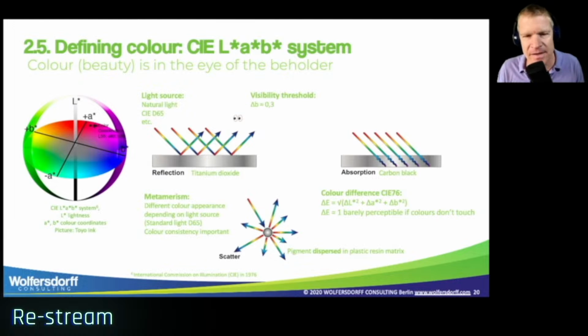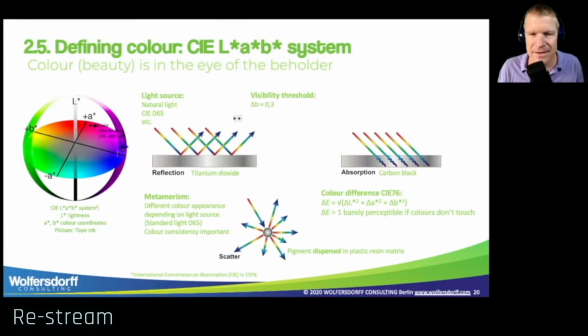And then looking at the masterbatch, we have several mechanisms by which the light can engage with our pigments. That could be reflection, which is the case of titanium dioxide, with the highest refractive index of all materials. This is the reason titanium dioxide is used as a white pigment, because all the light is reflected. It could be absorption, which is the case of carbon black. So we expect from carbon black, and also from recovered carbon black, to absorb all the light and to appear black, because black is the absence of any light. And then we might have scattering effects, when the light comes onto the particle and is scattered from that particle.